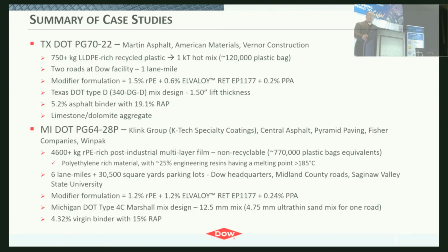And because that was a little bit bigger project, we did use around 4,600 kilograms of this rPE. That was the equivalent weight of over 770,000 single-use grocery bags. We also paved a project at Saginaw Valley State at the end here, and the formulation was 1.2% recycled material, 1.2% ELVALOY. This was a Marshall mix design.